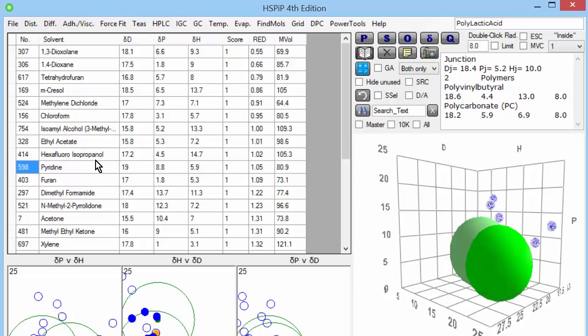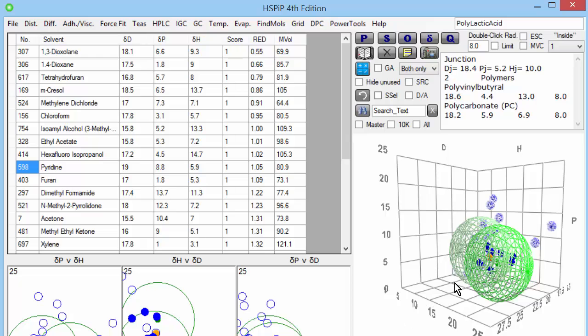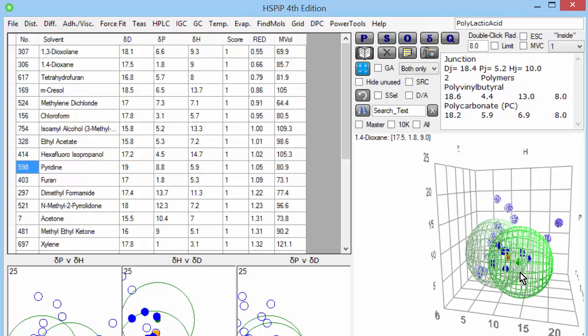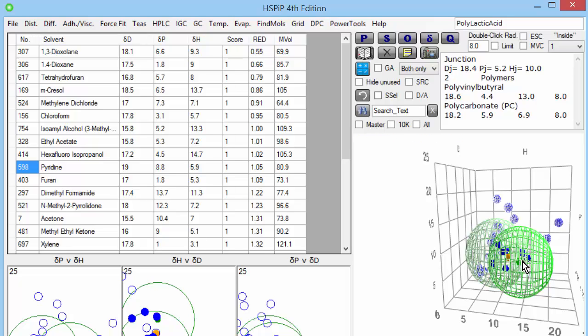We have this set of solvents which I've kept from the polylactic acid example just for familiarity. We see two spheres in here — it's a bit difficult to know what's going on. So I'll click the wireframe option, and these now appear as wireframe drawings. When I rotate the 3D you can see a golden dot in the middle. That is the HSP of the junction between these two polymers — an HSP of 18.4, 5.2, 10.0 — the ideal place for a solvent which would be between the centre of the polyvinyl butyral and the centre of the polycarbonate.